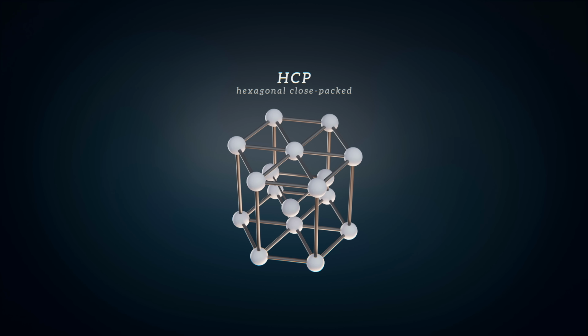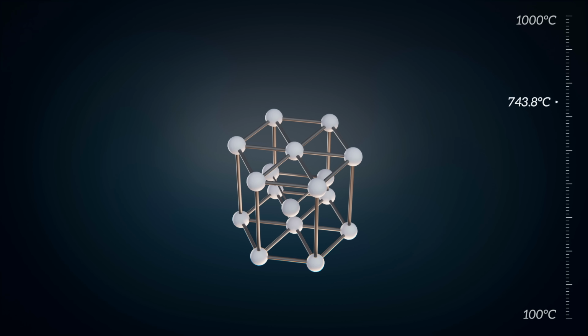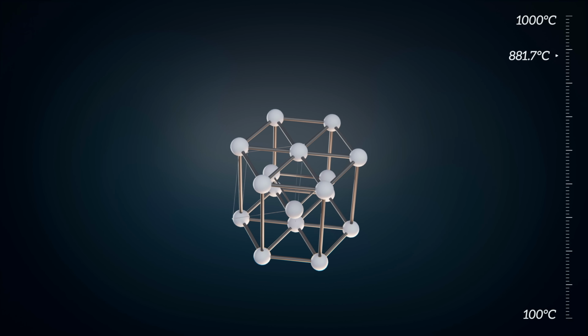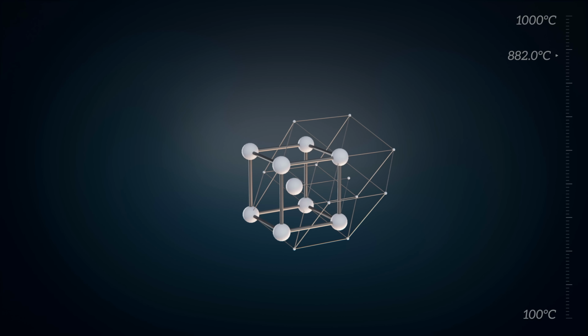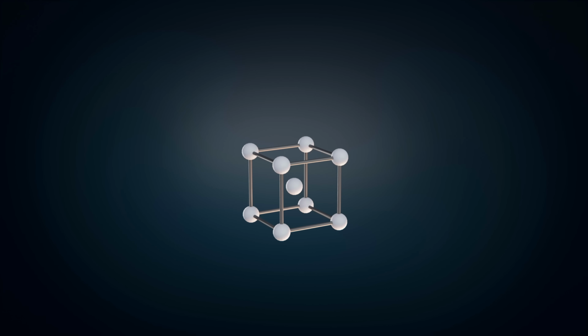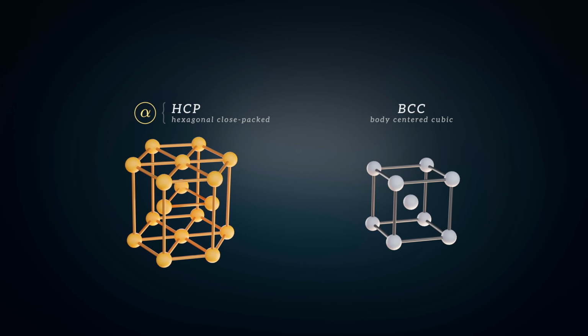Heated up, though, at 882 degrees Celsius, the atoms suddenly become more stable in a different configuration and undergo a phase transformation, rearranging from hexagonal close-packed to a body-centered cubic structure where the atoms are less tightly packed. The lower temperature HCP structure is called the alpha phase. The higher temperature BCC structure is called the beta phase, and the temperature at which the transformation occurs is called the beta transus temperature. The alpha and beta phases behave quite differently because of their different geometries.